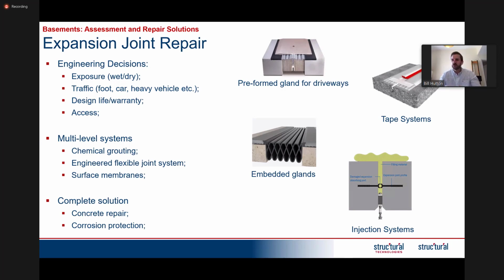In terms of different repair systems, there's lots of different repair systems available. So I just put a few examples up here. You can have a preformed compressible gland system for a driveway, which may have a protective aluminium or metal cover plate over the top. There's also tape systems. Tape systems could be installed on the surface of the concrete. Generally, they're bonded with an epoxy adhesive, or they could actually be embedded into the concrete. So you would excavate, say, 50 or 75 millimeters down and put the tape system in, and then put a grout material over the top, obviously making sure that you have that movement available in the middle.